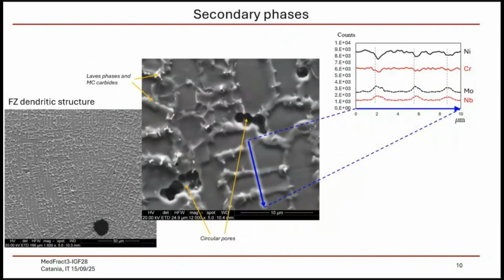Some final considerations about the possible presence of secondary phases. Here we have a micrograph of the dendritic structure inside the fusion zone. And as you might see, first of all, you can see some circular pores that are probably related to trapped gas because of their morphology. And then you see there are some shiny particles in the interdendritic areas. These are claimed to be, in the literature, Laves phases or MC carbides, mainly niobium carbides, considering the alloy. And indeed, with EDS line scan analysis, we could see that in the interdendritic area, we have depletion of nickel and chromium and richness of molybdenum and niobium.